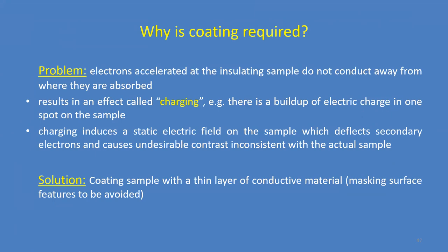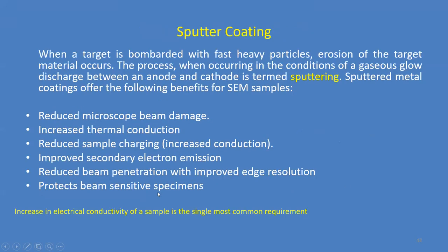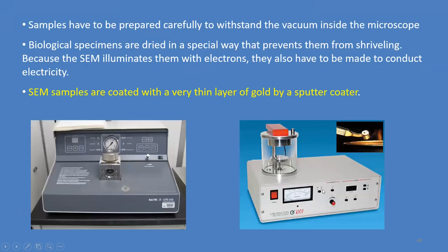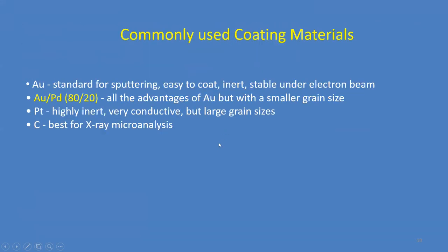And then after you do this, you have to make your samples conductive so as to avoid the charging effect. So you have a sputter coater. The solution is to coat your specimen with a thin layer of gold. The idea is to increase the electrical conductivity of the sample so that you don't have charging effects. This is how the sputter coater looks, and this is a critical point dryer. Typically you coat with gold or gold palladium.